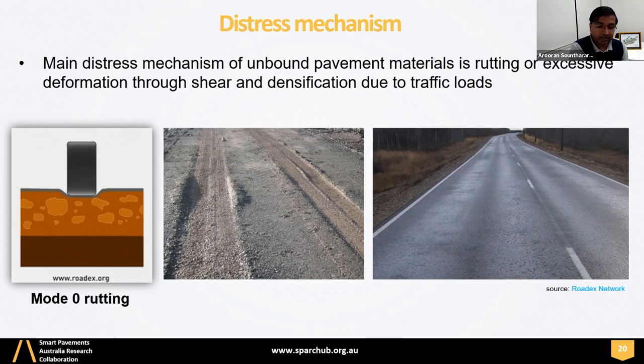However, this mode of rutting is usually self-stabilizing. Some people call it a shakedown of the material. So although your compaction roller compacted this material, what happens under traffic, which is a more dynamic and repeated load, is that these unbound granular particles try to stabilize themselves when the traffic dynamic load is applied, and position themselves into a stable state. Therefore, you see some sort of initial rutting occurs.